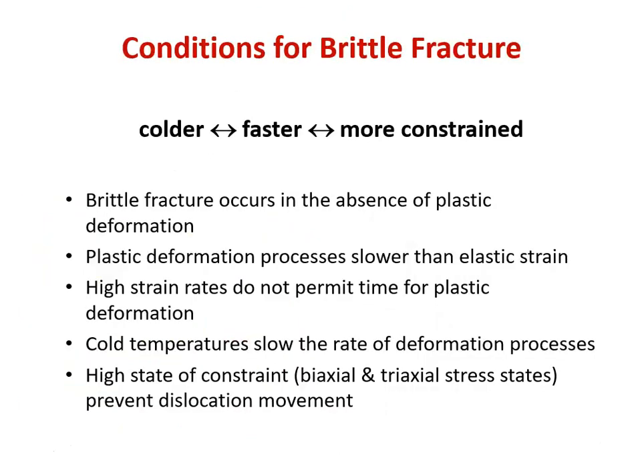Okay. General conditions that favor brittle fracture. So this would be true for any given material. Obviously, some materials will tend to fail in a brittle manner regardless of what we do, like ceramics or tungsten or very brittle metals or heavily, heavily cross-linked network polymers. But a lot of materials could behave either way depending on how they're loaded and the conditions under which they're loaded. So for those in-between materials, we can consider things that will tend to make them fail in a brittle manner and things that will allow them to fail in a more ductile manner and give them a higher fracture toughness, which we generally want in service.